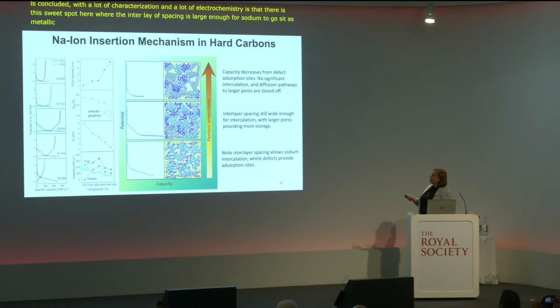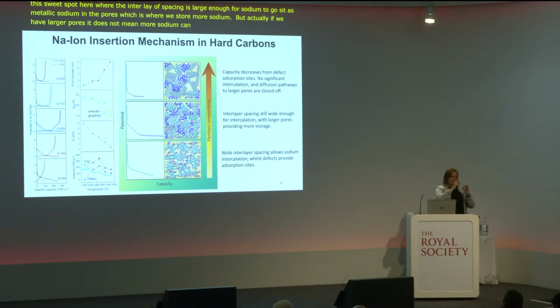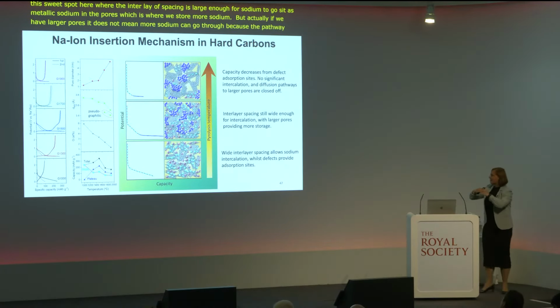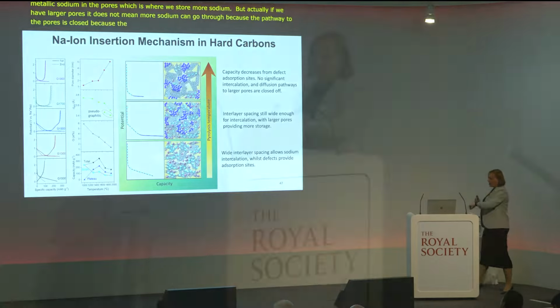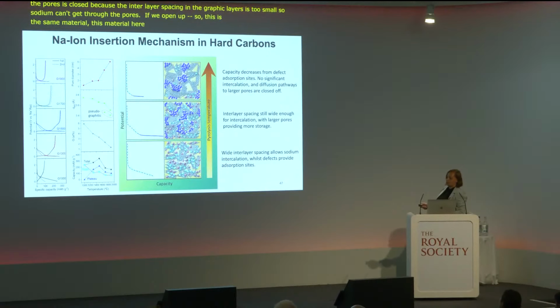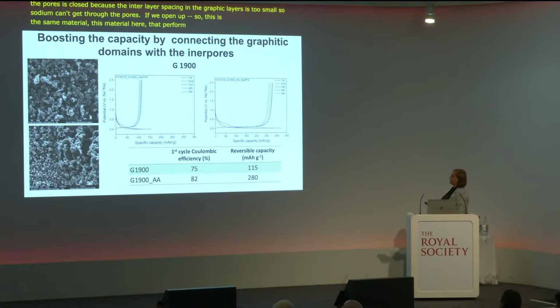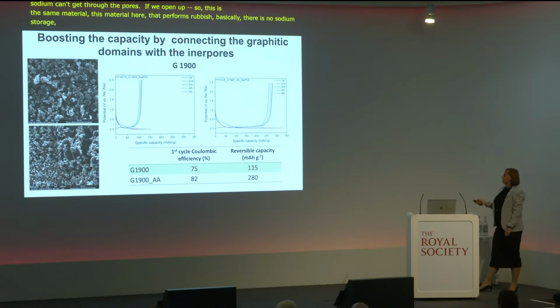But if we have larger pores, it doesn't mean that more sodium can go through, because the pathway to these pores is closed: the interlayer spacing between these graphite layers is too small, so the sodium can't get through. And this is the same material, this one here that performs rubbish, basically there is no sodium storage, no plateau. Once we open up the pores, you see that you open up the capacity.